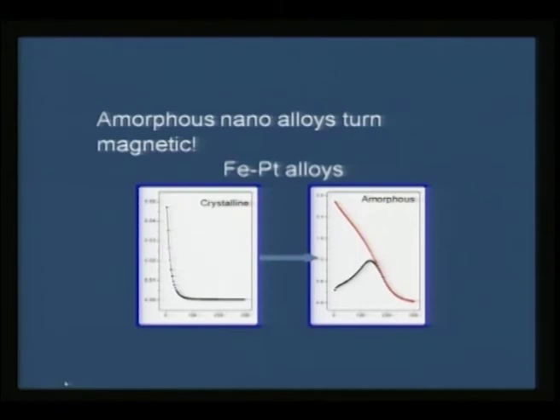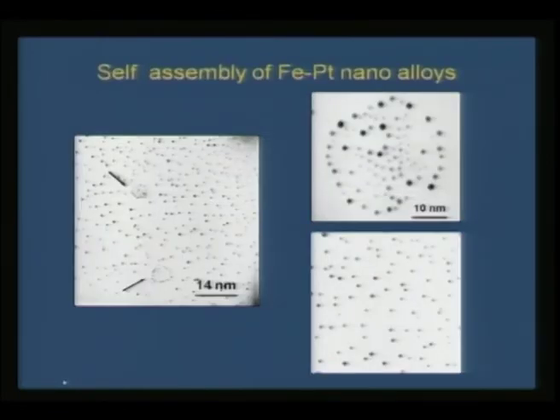Another interesting alloy is iron platinum nanoalloy. We can prepare it in amorphous nano form, but there are interesting features that we see in iron platinum nanoalloys. This is the resistivity curve for a typical iron platinum nanoalloy prepared by sonochemistry, where you can see a crystalline one shows a resistivity curve like this, and the amorphous curve actually shows the magnetic transition in a peculiar form. Let me bring forth some examples of that.